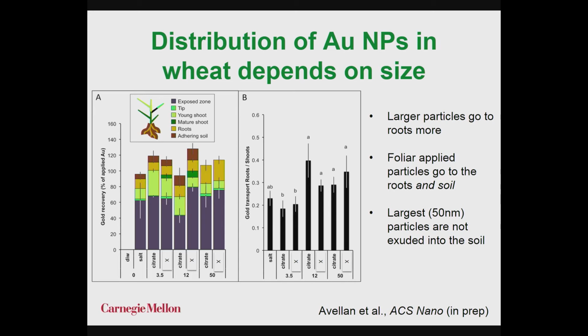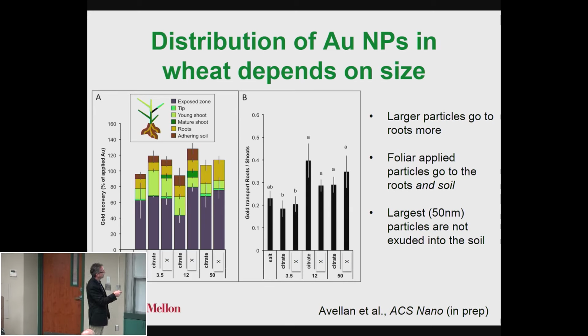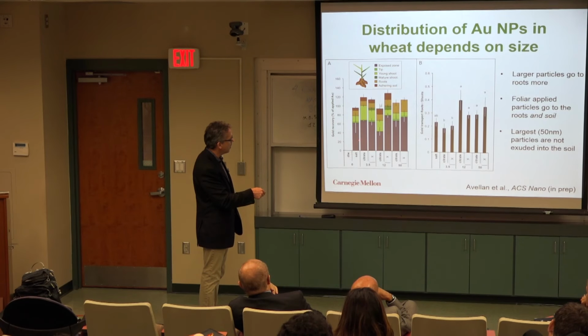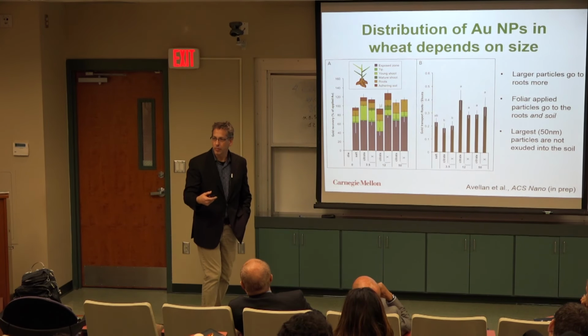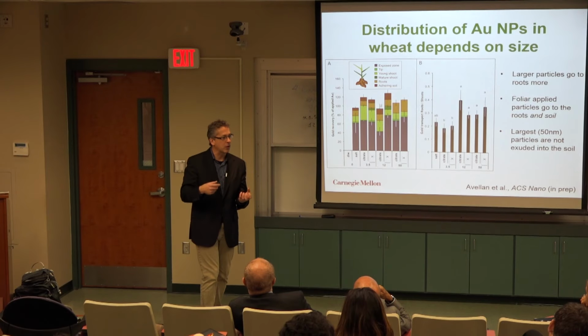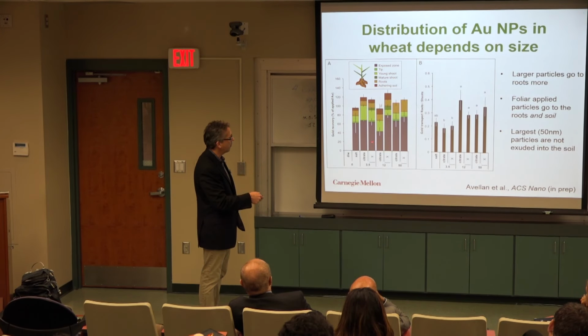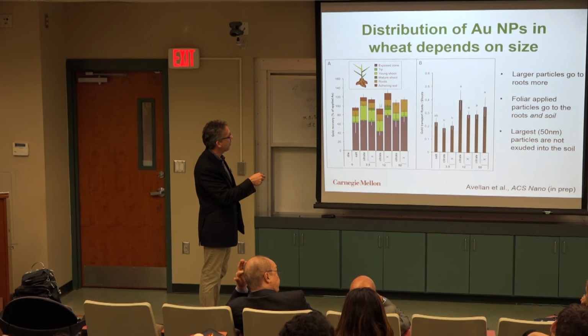Now, we do whole plant experiments too. We take these plants, we take the roots and the leaves, we digest them and we measure total metals. And sure enough, you find that most of the gold, this is by size and different coating, is on the leaf where we put it, either on the outside or stuck inside. About 50% of it is on the leaf. The other half has moved. It's moved to the younger shoots, it's moved up, it's also moved down.